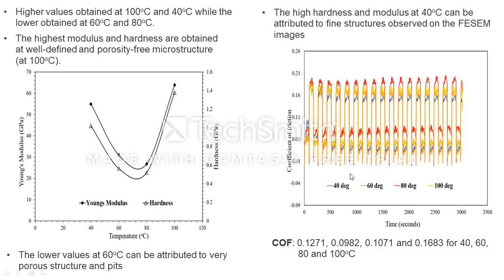As such, we did microwear analysis for 3,000 seconds. The coefficient of friction against time is shown. We were able to get this average stable coefficient of friction for the 4 samples. It was found that the highest average coefficient occurs at 100 degrees, which shows that these samples have the highest resistance to mechanical degradation or to wear. Also, the samples at 40 degrees had a higher resistance to sliding wear, and this could also be attributed to the fine microstructure, and higher hardness and Young's modulus.